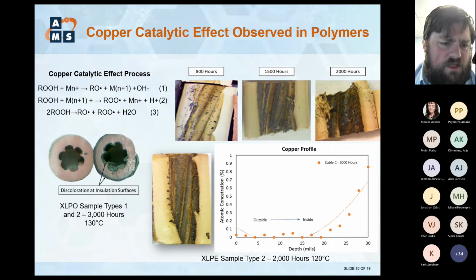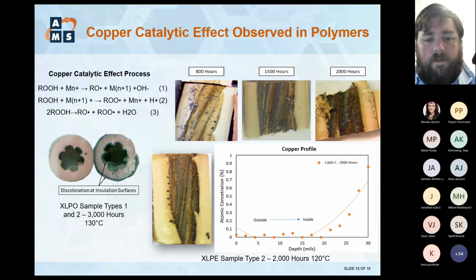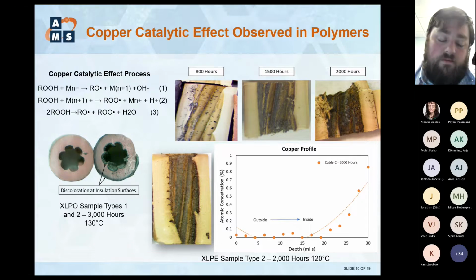And so you can actually see, on the left is some of the discoloration we've seen in cross-linked polyolefin insulation, both at the exterior surface but also at the interior surface where that copper catalytic reaction is happening. And then in the bottom right corner of the screen is XLPE sample type 2 insulation we've tested after 2,000 hours of aging at 120 degrees Celsius.